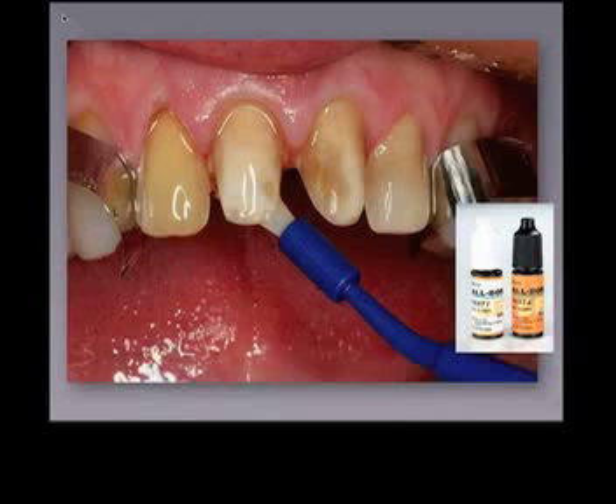You'll note that most manufacturers state 10-second air drying, but All-Bond SE contains significantly more solvent than Total Etch, so it's recommended to air dry for 20 to 30 seconds depending on your access. Non-evaporated solvent significantly affects the bonding interaction, so just air dry it for 20 to 30 seconds and get all the solvent off.